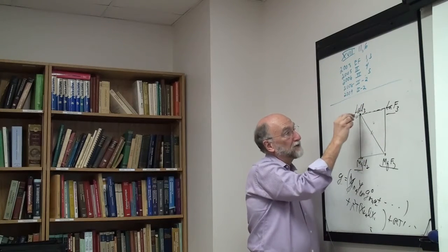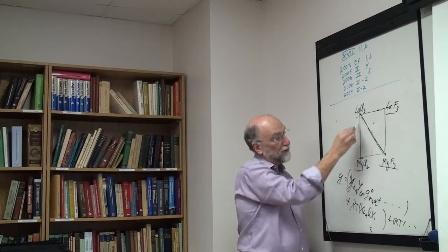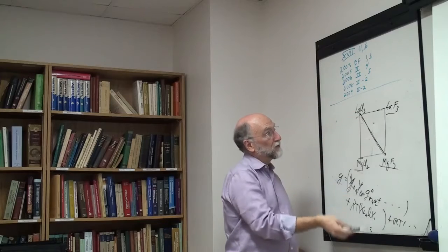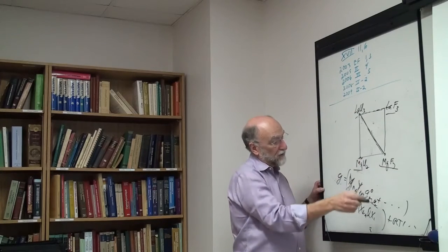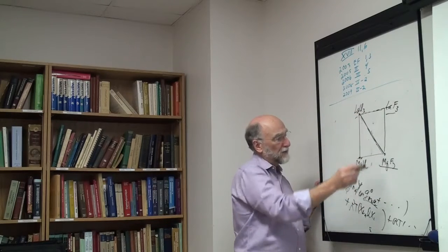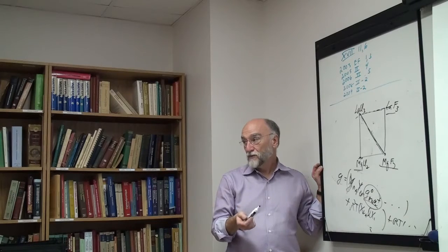This could even be your stable pair over here, for that matter. Now, if this is a very stable pair, then most of the tie lines will lie over here. This will be a quasi-ternary system, but you still need this model. And remember, the most important thing in any reciprocal system like this are these G naughts. The delta G exchange is the most important term.